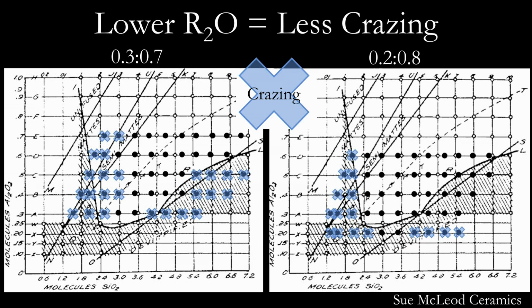And the last most interesting thing to notice is that map number 2, 0.2 to 0.8, has a significantly lower number of crazed samples than map number 1. The reason being, sodium, the R2O flux, has a higher thermal expansion than calcium, the RO. Map number 1 has a higher proportion of sodium than map number 2, therefore map number 1 has more crazed samples.